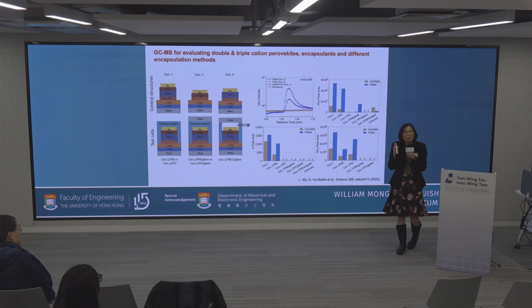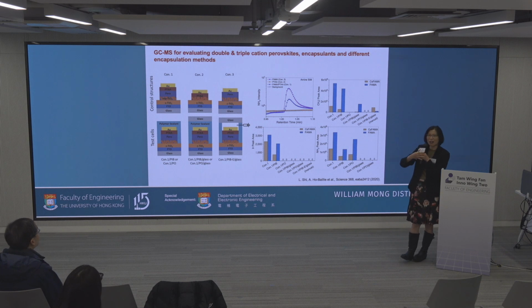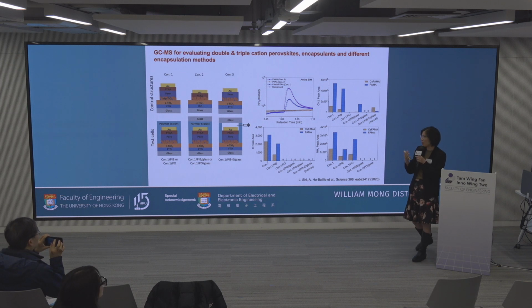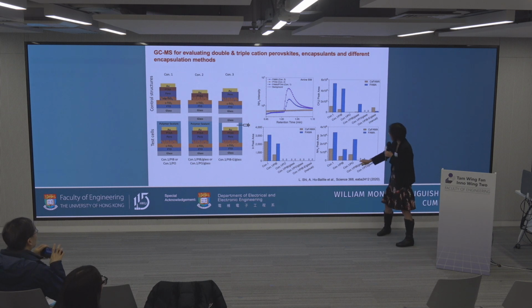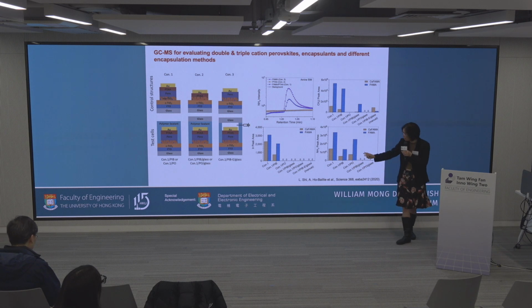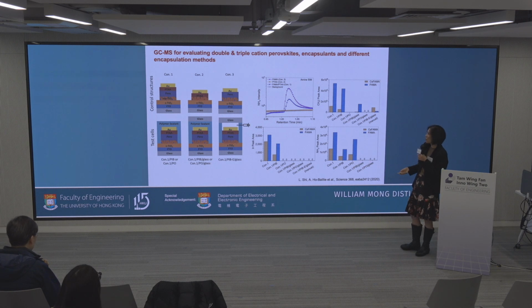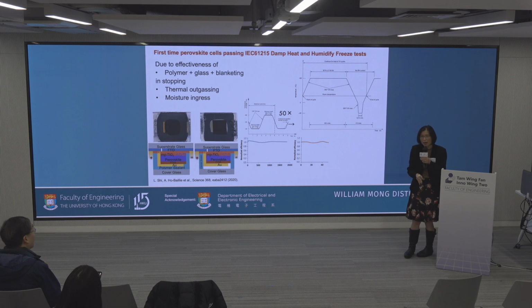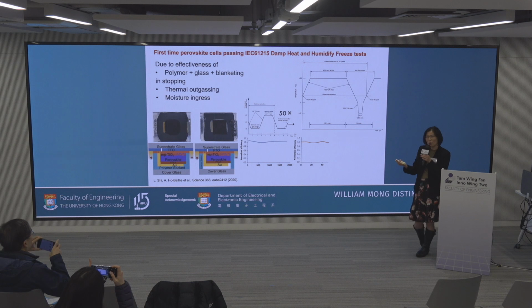We found that you need the blanket. You need the blanket to cover the perovskite so that you don't have a void for the outgassing to come out. So that stops the outgassing, and we also looked at the impact of the difference between PIB and POE. The conclusion is you need a polymer, you need glass, you need both of them, and you also need the blanketing to stop the thermal outgassing. And when you can suppress that, you can suppress the decomposition. And of course, the encapsulation also stops the moisture ingress.